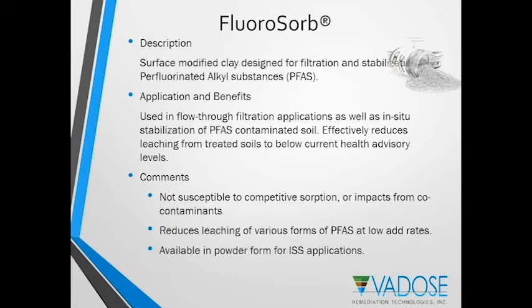One thing that's unique about this FluoroSorb technology is that it's not susceptible to competitive sorption or impacts from co-contaminants. Other filtration media, such as granular activated carbon, is much more affected by co-contaminants that might take up sorption sites or in fact kick off contaminants that have previously been sorbed.